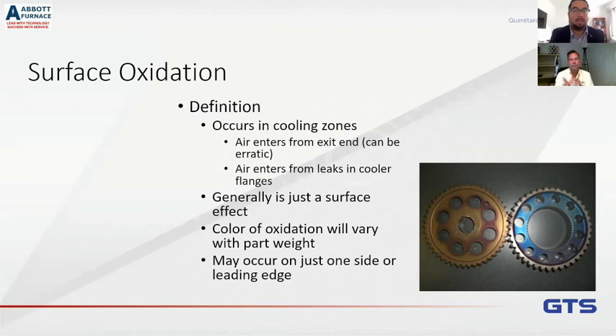Well, it really depends on how you're processing your part. If you're using exo, you have that extra element there of the CO, whereas if you're doing hydrogen, nitrogen, it would only be air or water, because you aren't seeing the CO component. So if you have a generator issue, that could also cause discoloration. Again, that's the importance of measuring the atmosphere. You will know exactly what is going on inside and where the problem is. And also, measuring the incoming atmosphere will tell you if your problem is at your generator or in the furnace.